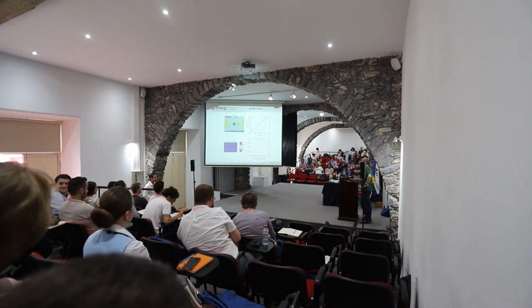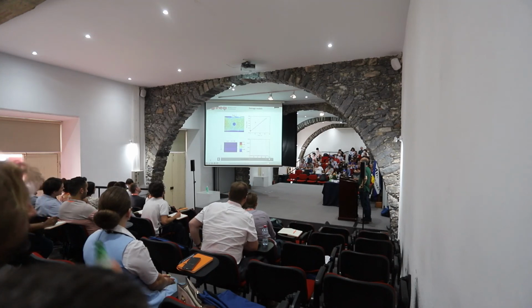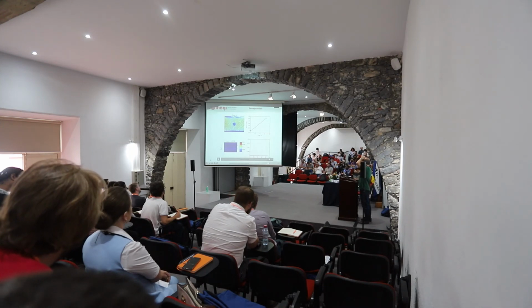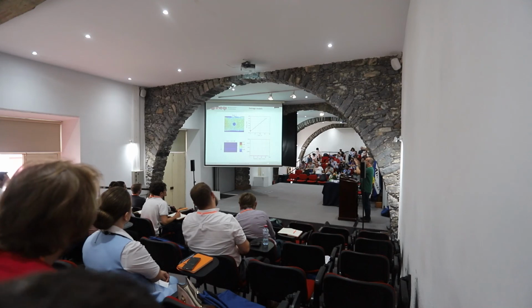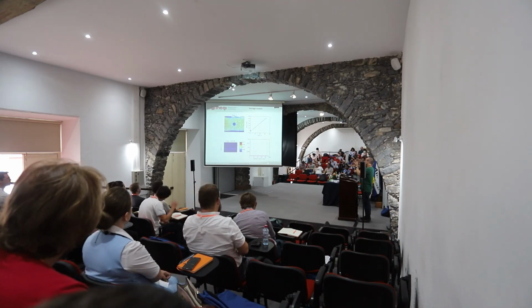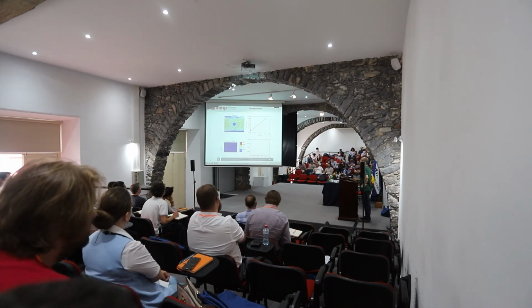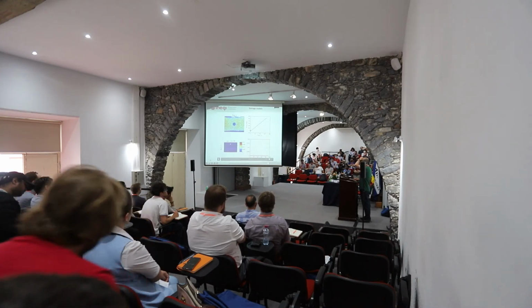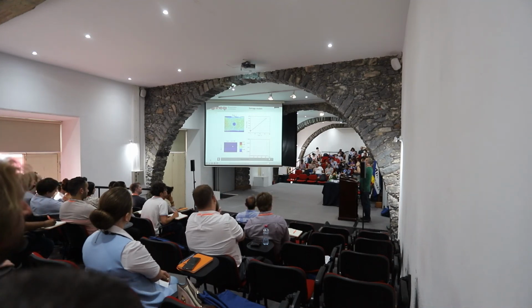Yes, that's a nice picture. What you can see here, it's not a modern art painting, it's an open hole tension specimen with a speckled pattern on the surface. So we have a 90-degree ply there. And really to show you the importance of and the distinction between first ply failure and last ply failure and the need for a damage model, it will become clear here. This is open hole tension with a 90-degree ply on the surface, stress versus time, experimental. And here, this is the strain field in the loading direction.